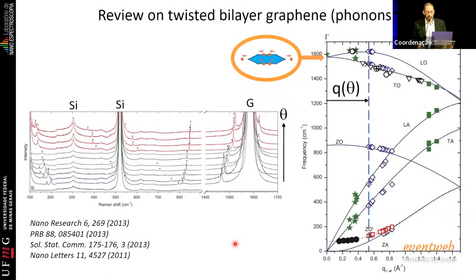Okay, so if I go back to the picture that I was showing you, this vibration is actually seen here at, as I said, near 1600 wave numbers. And when you look into the phonon dispersion relation for graphene, this is equivalent to this point here. So this is what you see, okay? But when you have twisted bilayer graphene, as I told you, you reduce the reciprocal space, the Brillouin zone. And what you are doing is activating phonons in the interior of the Brillouin zone. And actually with all these peaks here, you can map the entire phonon dispersion relation of graphene just by rotating these two layers, okay?